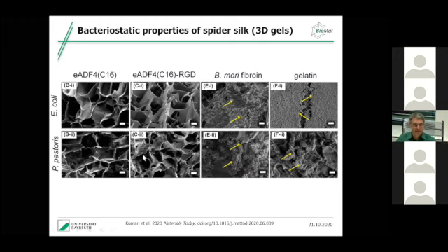So actually what we did, we floated these hydrogels with bacteria and yeast. We incubated that for days. And then we just washed it. And you see that both spider silk hydrogels, they're absolutely clear. There's no single bacterium in there. And the silkworm hydrogel and the gelatin hydrogel, they're actually grown over with the bacteria and with the yeast.